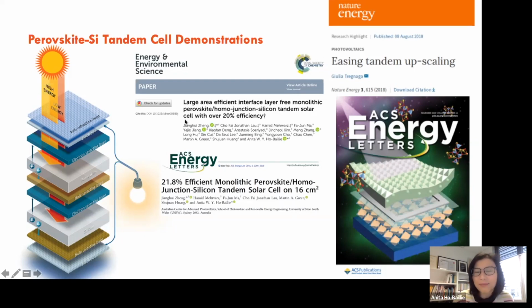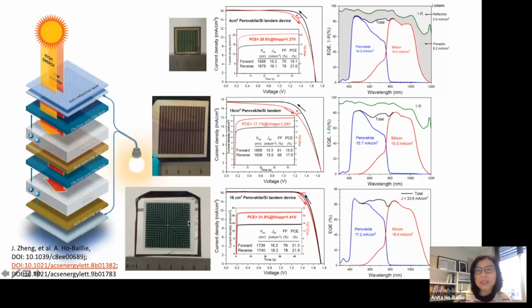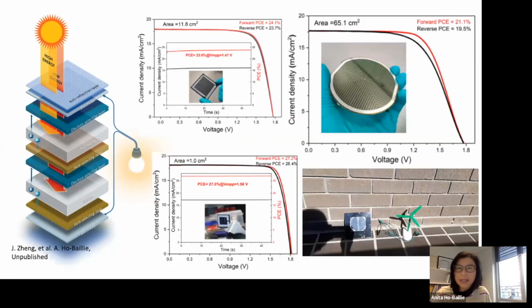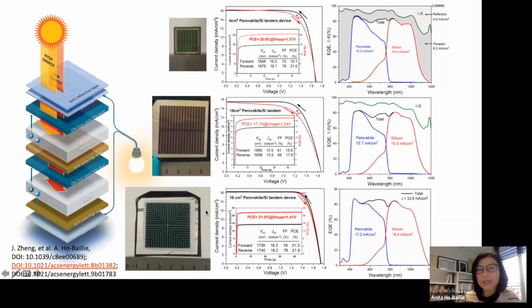Over the years, we have been trying to improve the efficiency of the cell, as well as increasing the size of the demonstration. That's because a lot of people, when they work on perovskite cells, make them on tiny, millimeter size cells, but we say no, we want to make it in bigger size so that it's industry relevant. And when we scale it up for our industry partner, they're able to do so. Another advantage of our design is we try to make it very simple. In some research labs, they have an extra layer between the electron transport layer and hole selective layer to integrate the perovskite and silicon.